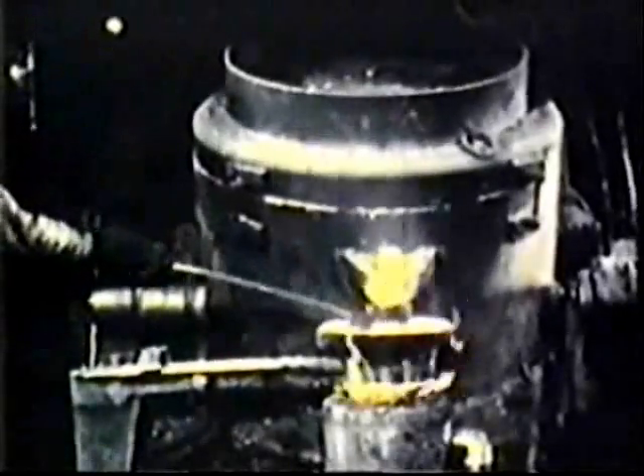While the heat is being poured, the caster secures a sample. The heat number is stamped on the sample, and it is sent to the laboratory for chemical analysis. The sample is drilled, and the drillings are weighed, then dissolved in acid and titrated or electro-deposited to determine the copper content. This test is always completed before another heat is poured. By this method, the composition of the cast metal is immediately determined and any necessary adjustments can be made.